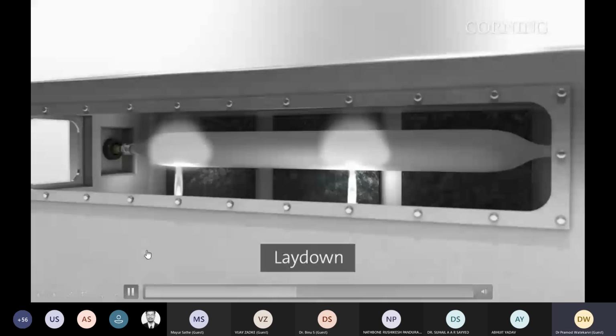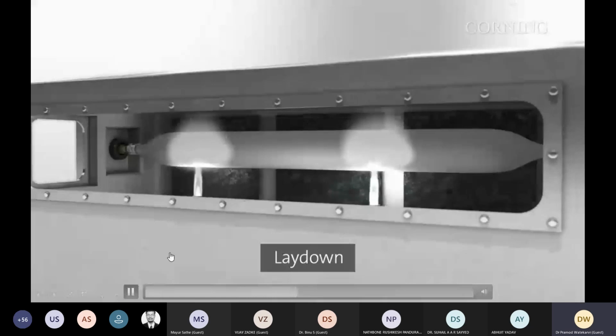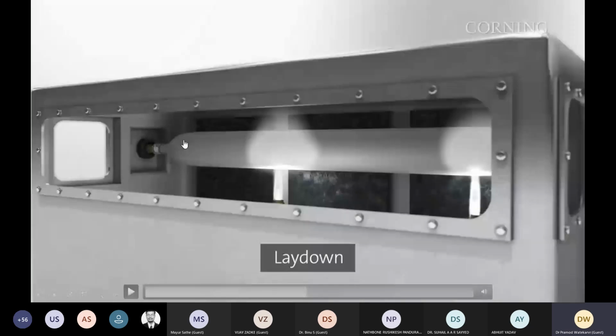So as you can see, its diameter is getting increased because we are continuously depositing SiO2 and GeO2 particles. So it's a soot, and it takes around 10 to 12 hours to get 100 mm diameter.